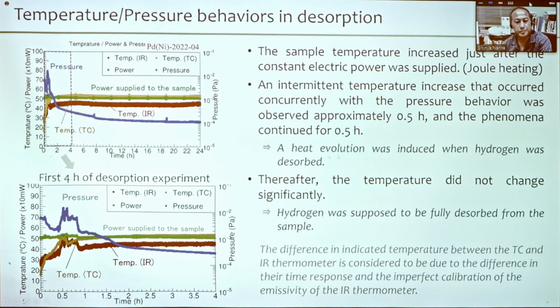So it seems the heat evolution was induced when the hydrogen was desorbed. Then thereafter, the temperature did not change significantly. So now we suppose that hydrogen was fully desorbed from the sample in that period. And note that there is a difference in the indicated temperature between the thermocouple and the infrared thermometer. So this is considered to be due to the difference in the time response and maybe imperfect calibration.